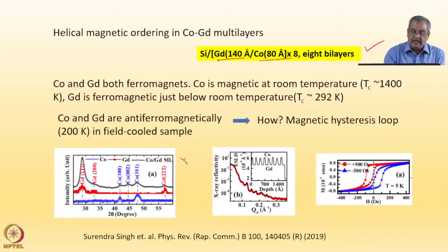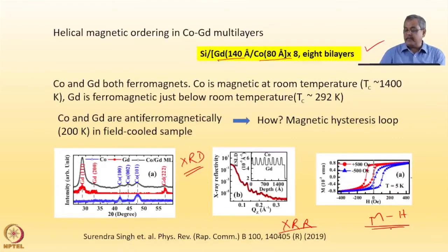One is XRD, which says that it's a polycrystalline sample. XRR gives me the scattering length density or the physical density as a function of depth, and then the magnetic hysteresis loop. Now this magnetic hysteresis loop, interestingly, I just show you the hysteresis loop at 5 Kelvin under a field cooling field of 500 oersted plus and 500 oersted minus. You can see the shift